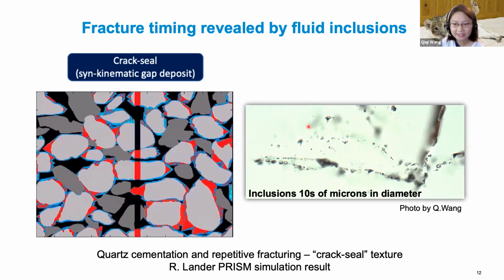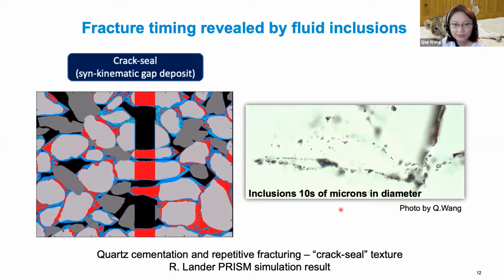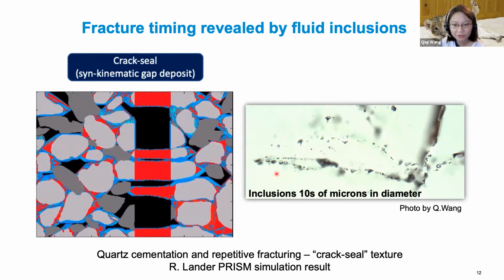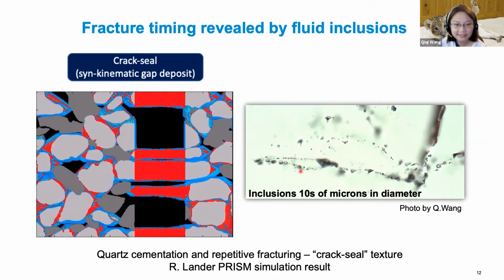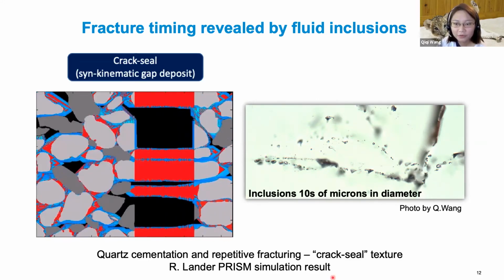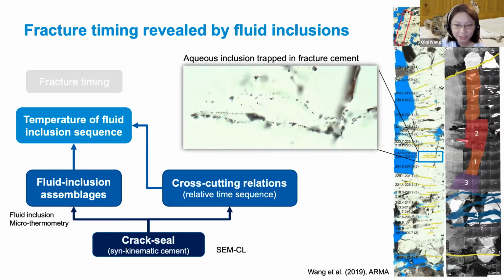So in this picture, you can see individual inclusions forming trails of inclusions trapped in the crack, and we call the trails of inclusions a fluid inclusion assemblage. The fluid inclusion assemblages can tell us the temperature, the composition, and the pressure of the fluid flowing through the fracture when it was forming. Then we can put those trails of inclusions in relative time sequence based on the cement texture. For example, on this image right here, the zones 1, 2, 3, 4, and I also have a 5 here are sorted by age. With 1 being the oldest, and 4 and 5 being the youngest.